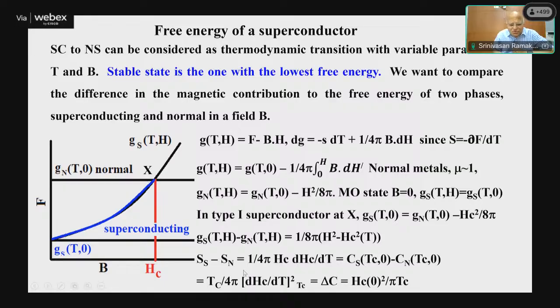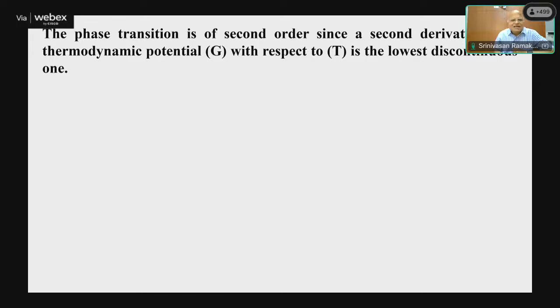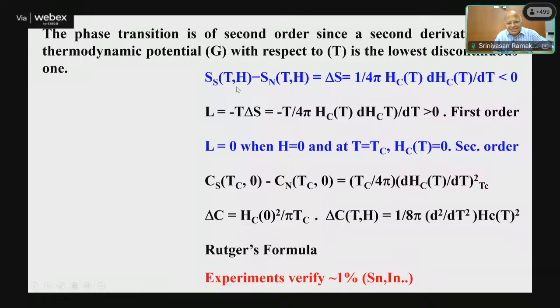So you can also compute the discontinuity, the jump in the heat capacity, which is given by the critical field divided by the transition temperature. So the phase transition is second order, since the second derivative of the thermodynamic potential is discontinuous. So you can see that the entropy change is given by this expression, where you see the associated latent heat, which is given by this. When you apply a magnetic field, it becomes a first order transition. Remember that the superconducting transition is second order in the absence of a magnetic field, but it becomes first order when you apply a magnetic field.